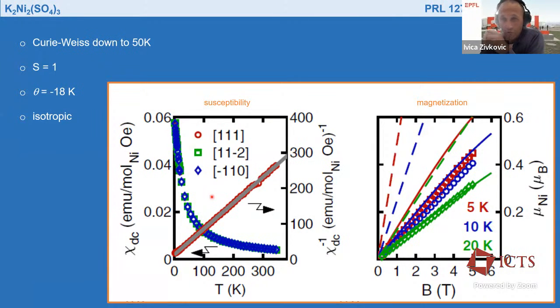The g factor is 2.34, so that indicates that it could be, but those are actually typical values for nickel. If you look at nickel and ESR, it's not strange to see it. So I would say it's not anything special in terms of what could be expected from nickel. Now, if you look at cobalt, I would expect the anisotropy to be much more strongly felt there. But then again, there you actually have these structural phase transitions, and the suspect is the SO4 group, which freezes. So you have some modes which fluctuate, and then when those freeze, you have the structure. So still, at low temperature, one should be able to address the question of anisotropy by investigating the cobalt version. For us, it seemed that nickel is as good as isotropic. Thank you.